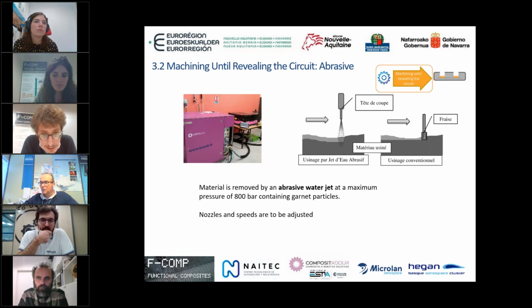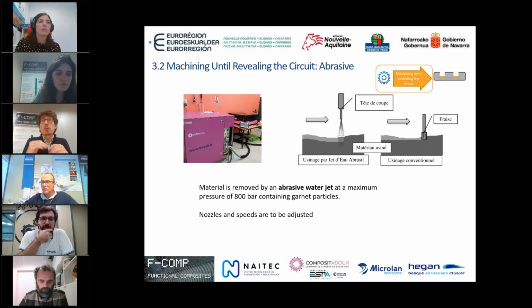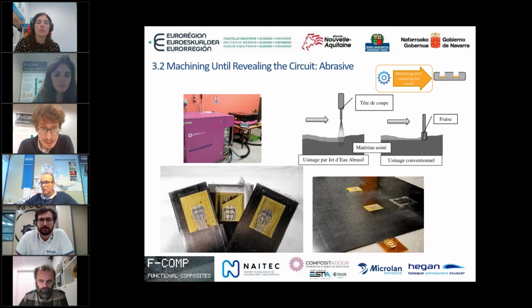As well, taking the opportunity that in COMPOSITADOUR there is a machine by Bayab that makes abrasive water jet machining, we did some trials. This machine just uses some nozzles that put water containing garnet particles at a pressure up to 800 bars. And it moves over the surface, as you have seen in the video, removing part of the surface just by abrasion. The point here is just selecting the proper pressures and the speed of the movement of the nozzle. This way, you manage to have more or less revealing of the surface. You can see in these photos what is the final aspect of the samples.